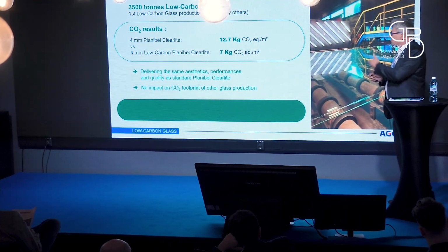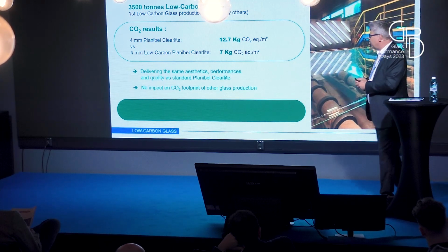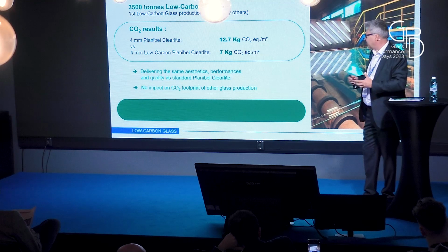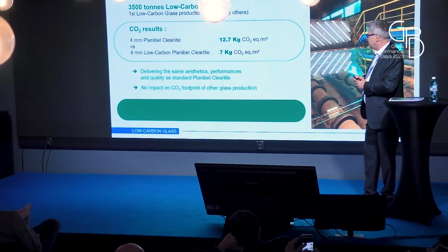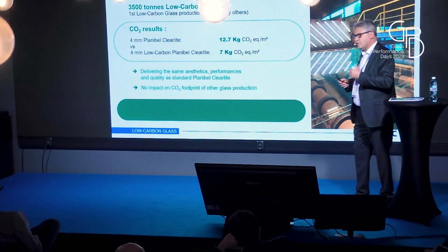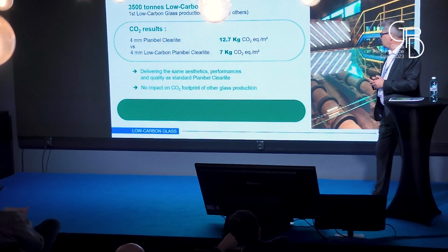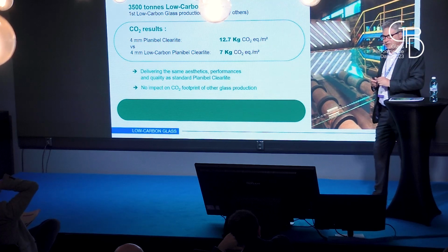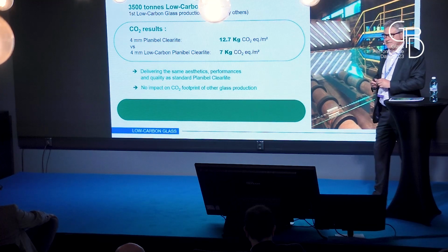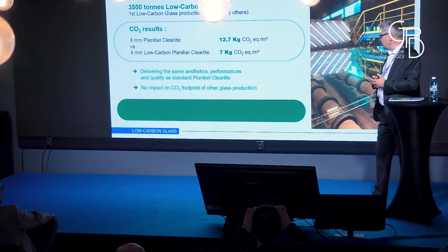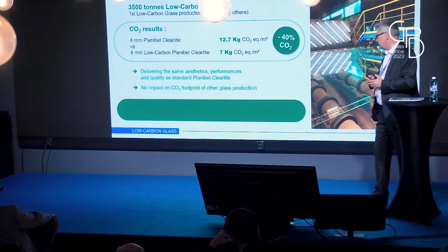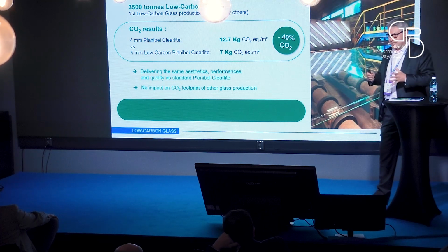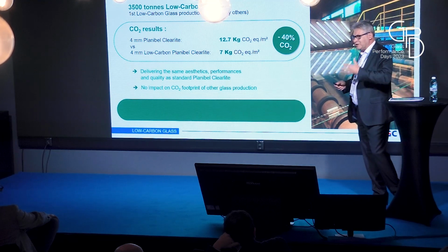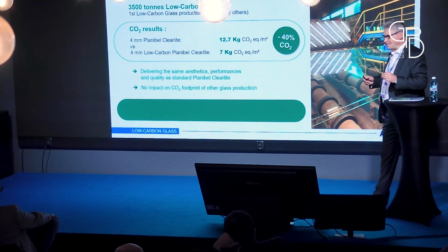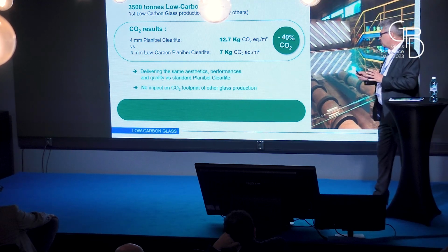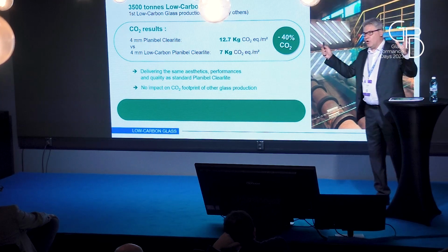As a result, during the first production, but we do other production after, we produced 3,500 tons of low carbon glass. This low carbon glass shows 7 kilos of CO2 equivalent per square meter, 4 millimeter clear float, versus 12.7 for our European value. So it's a reduction by more than 40%. What is important is that it is the same glass with the same aesthetic, the same light transmission, the same haze, exactly the same glass. And also, we take care to have no impact on the CO2 footprint of the other production.